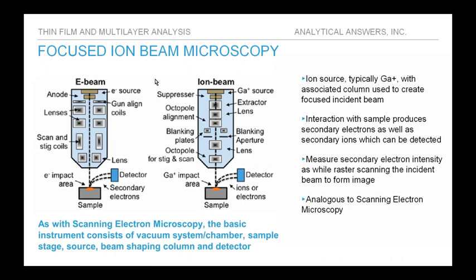For those of you who may be unfamiliar with the technique, it's very much analogous to scanning electron microscopy. In the scanning electron microscope, we generate an electron beam that we use to probe the sample surface. In focused ion beam microscopy, that's replaced with a focused ion beam. The most widely used source is a gallium liquid metal ion source, which provides a very high brightness point source of gallium ions. There's an associated column that extracts those ions, accelerates them, and focuses them down onto the sample surface.